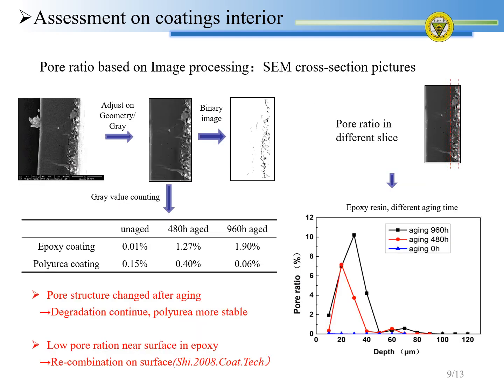Of course, we want to find some evidence that supports that the pores in the internal structure really increased. We analyzed the cross-section pictures of coatings and used image processing to obtain the pore ratio. We first adjust the geometry and the gray level of the image. Set a gray value as the threshold to distinguish pore and solid phase, and then count the pore ratio. Porosity of epoxy coating increases over aging time, while polyurea coating stays near zero. And we can find a denser surface on the epoxy resin coating. This confirms the existence of recombination and post-curing.